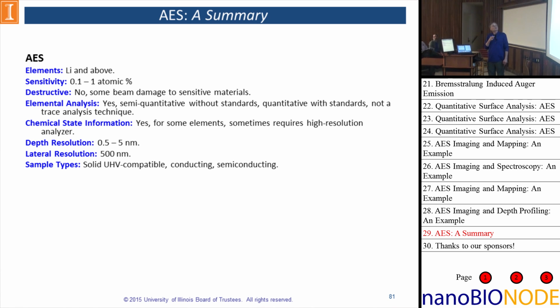Non-destructive, though we will suffer some beam damage if you have electronegatives. Mostly elemental analysis, semi-quantitative. Chemical state information from several elements, not for everything. It's not always as easy to extract as with XPS. Depth resolution comparable to XPS. Lateral resolution with our instrument is about half a micron. You can now go sub 10 nanometer with the field emission Auger systems.